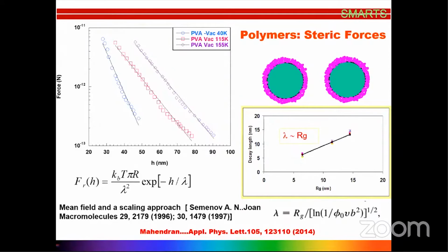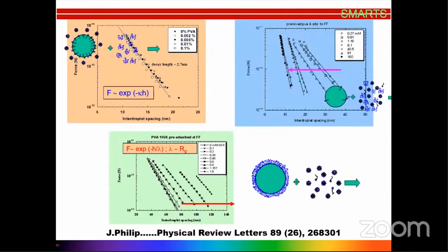And so this is a very well established technique to probe interaction forces at nanoscale. And we have also shown long ago that it can also be used to probe the polymer surfactant interaction. It's a very complex phenomenon which cannot be probed by any other technique except small angle neutron scattering. It's an indirect technique, and you have to go to cryo-TEM experiment. All this information you can draw by looking at the interaction forces.